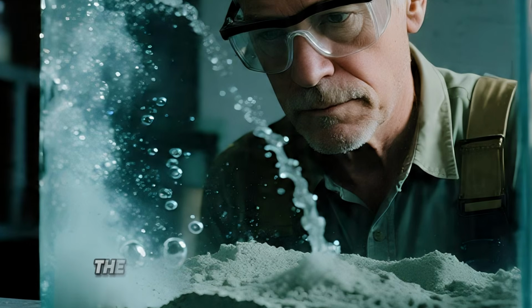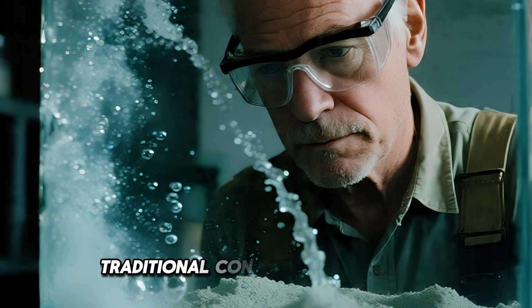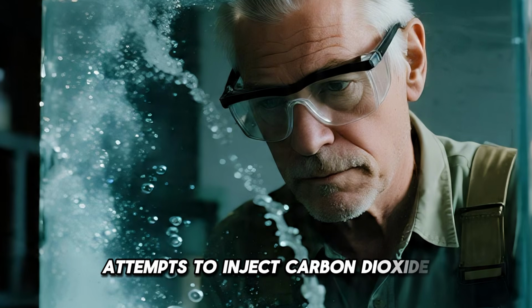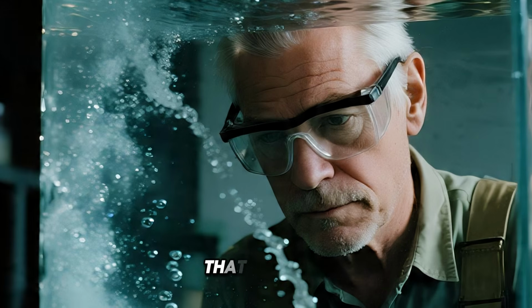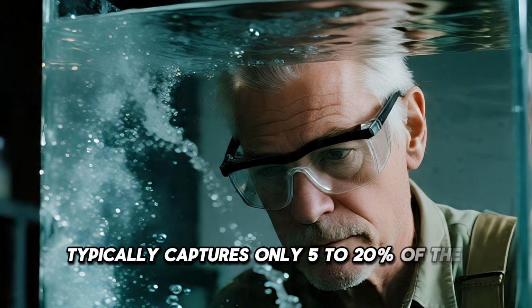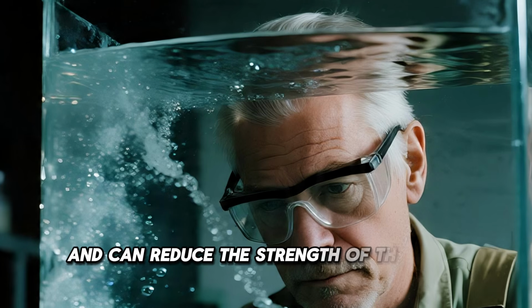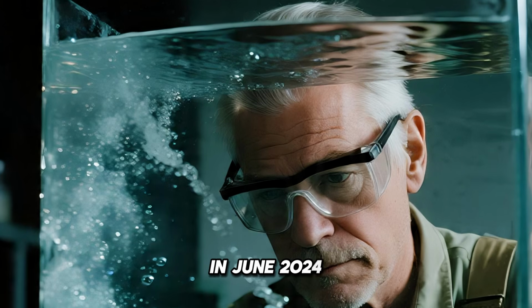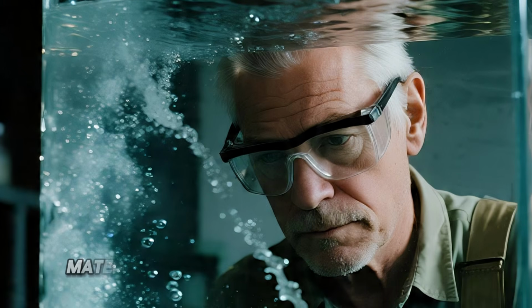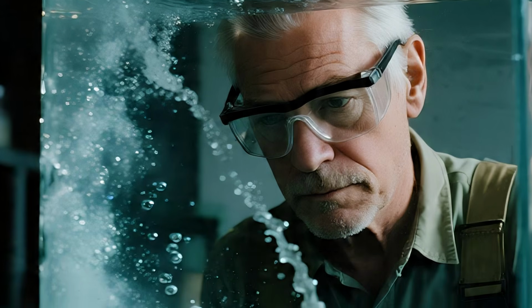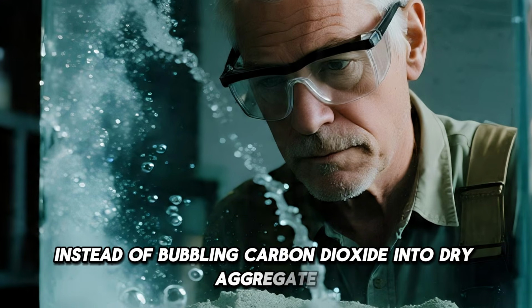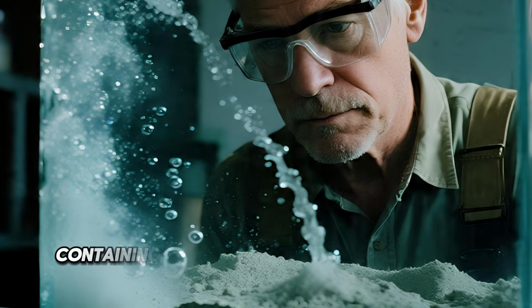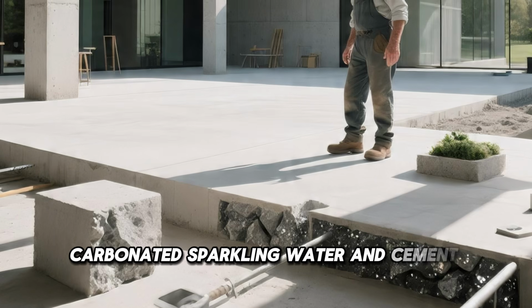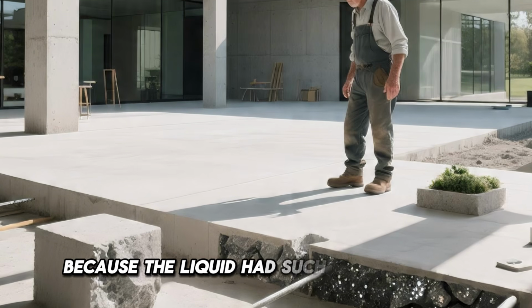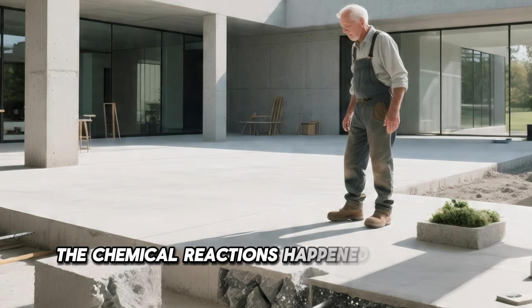They also reconsidered the way ordinary concrete is mixed. Traditional concrete carbonation attempts to inject carbon dioxide directly into a fresh concrete mixture. That process typically captures only 5 to 20% of the carbon dioxide and can reduce the strength of the final material. In June 2024, the team published another approach in Communications Materials called suspension carbonation. Instead of bubbling carbon dioxide into dry aggregate, they first introduced it into water containing a very small amount of cement powder. This produced a thin, carbonated, sparkling water and cement suspension. Because the liquid had such low viscosity, the chemical reactions happened extremely quickly.